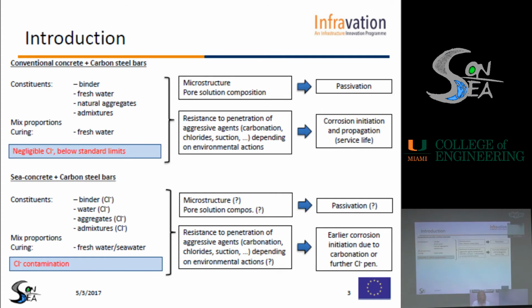In conventional concrete, that is a concrete made with virgin constituents, the chloride content is negligible and below the standard limits. So, thanks to the microstructure and the pore solution composition, carbon steel bar can be passivated. Then, in time, aggressive agents can penetrate into the concrete, leading to the breakdown of the passive layer, and so initiation of corrosion occurs, followed by the propagation time, which depends on environmental actions.